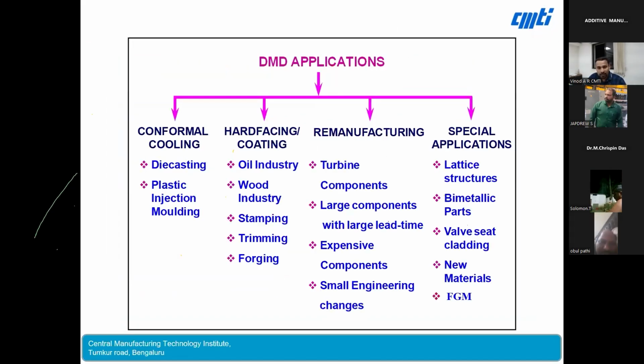So coming to applications, in addition to conformal cooling channel printing, you can also do coatings. For example, if you have an existing part, you want to coat upon that. Coating is not possible in the previous process, that is, in the powder bed fusion process, the DMLS process. Especially when you have a 5-axis 3D surface, you cannot do coating by powder bed fusion, because there you are spreading the powder layer by layer.